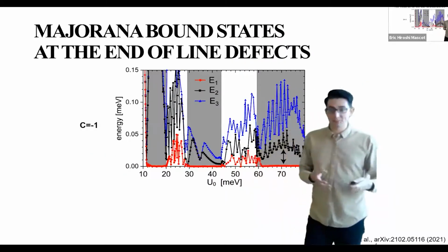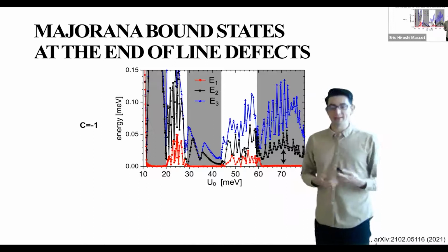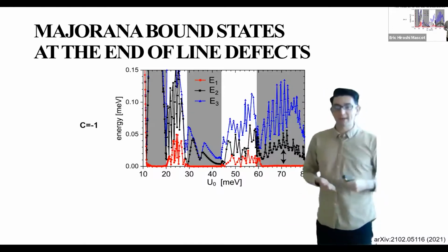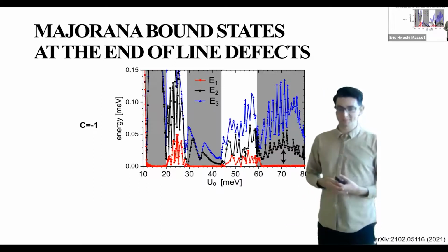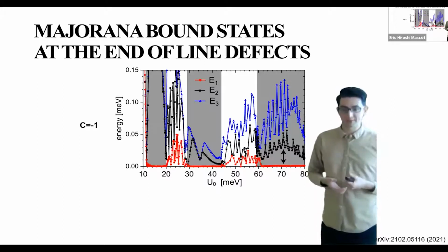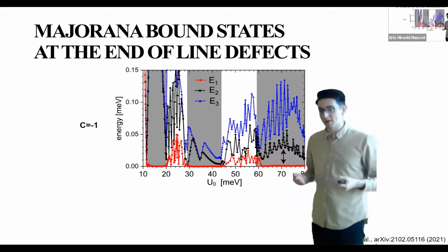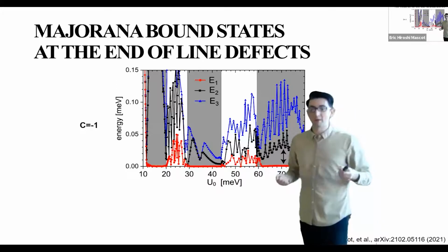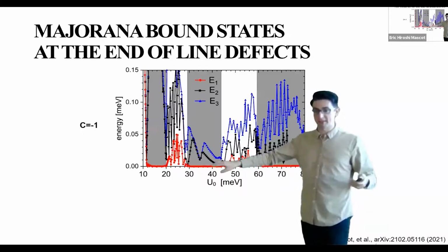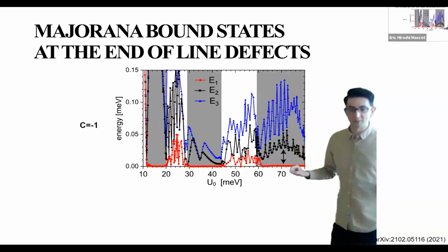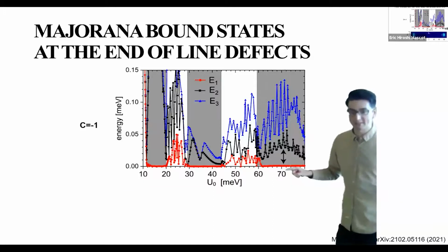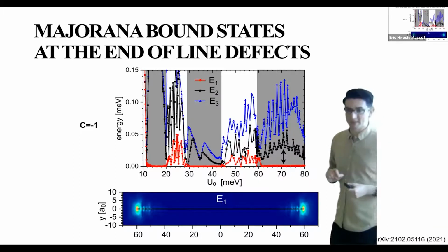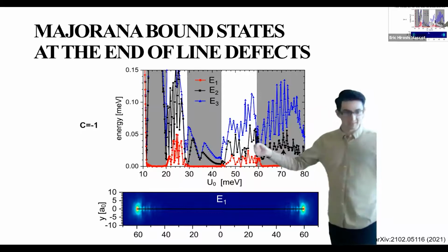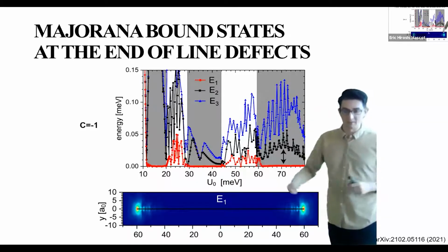For the next experiment, the line defects, we added a line of scattering potentials to our system. And for different scattering strengths, we found areas where you would get Majorana bound states at the end of the chain. Here we have our zero energy states. And if we look at this zero energy state spatially, we see that indeed it's a bound state at the end of the line defect.